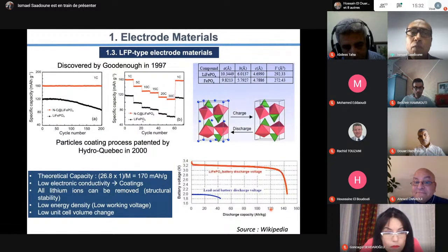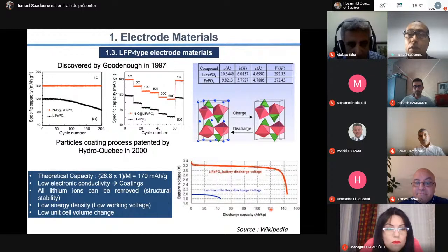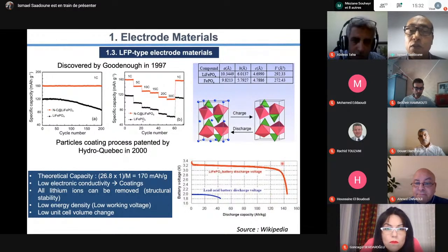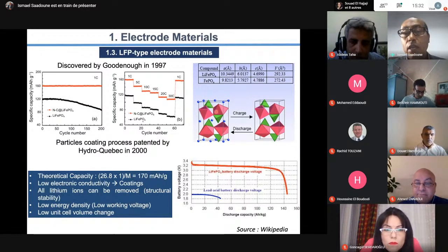The third example is LFP type electrode material. LFP is lithium iron phosphate. If you see here, this lithium iron phosphate is made from PO4 tetrahedra, and you have your iron in octahedral sites. So this is the discharge curve here.